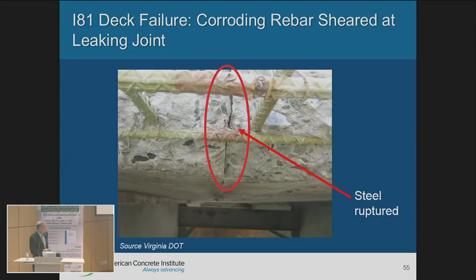Here's a picture that was taken from Virginia DOT, where they had a bridge, and there was a crack. I don't know if it was a crack intentionally put there or not, but those bars were epoxy coated. And if you notice, although with the epoxy, because of that crack, there is leakage.